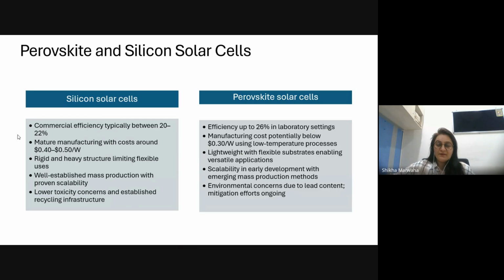Toxicity, this is a very important factor that I'll be discussing again in the coming ppts. Toxicity is something we have to address, because in perovskite we make use of certain layers, especially lead in the perovskite precursor material, which has a detrimental impact on our environment. Whereas in silicon, we do not have any such layer that would increase the toxicity. Yes, there is always toxicity when you're working on chemicals, but the level of toxicity is quite less in silicon. But in perovskite, there are chances that due to the increased lead content, it will have some detrimental impact on our environment.